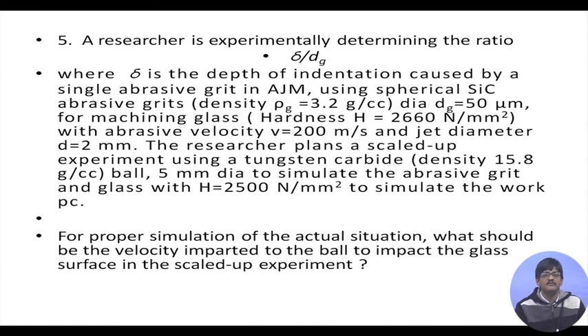5 millimeter diameter tungsten carbide ball. And what is he doing? He is taking as the work material a glass with hardness 2500 newtons per millimeter square. So, he will drop this ball, and this single ball will cause a damage of significant dimensions which he can measure. So, he is saying I will do this experiment with a single ball and get a very accurate representation of indentation at the lab level, okay,